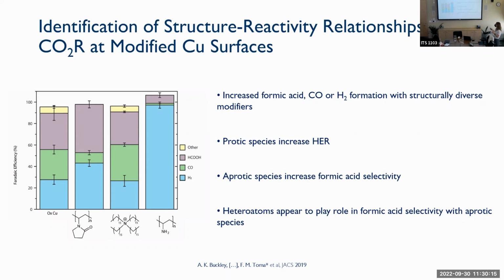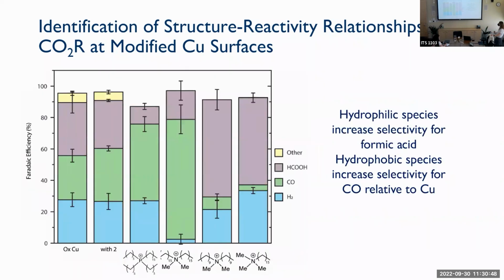And what you found is that when you use protic species, like in this case, you can have an increased HER activity. So the blue here is hydrogen. And then an aprotic species instead gives you more selectivity for formic acid, like the polyvinyl pyrrolidone case. And a case aside was represented by the ammonium salts that were having different behaviors with respect to the substituents. So here you can see more in detail the different roles of the substituents. You have alkyl chains with different lengths that are substituting this ammonium salt. By looking at the different lengths of the alkyl chains, you can see how you can become more selective for CO, or more selective for formic acid.